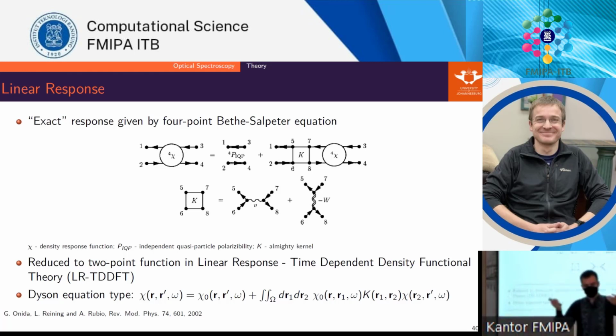So what an optical transition usually entails is the following. I have a material and I have presumably all my electrons sitting happily in the valence band in the ground state. Now I have a photon coming in, it gets absorbed. And it will excite one of the electrons into a conduction band. It will now be sitting up here at high energy. And it creates a hole where it was before in the valence band. Now the electrons in the valence band had a certain number of charges. Now we remove one, the charge changed by one. You remove this electron to a conduction band, you add a charge there. So basically now you have a negative free charge and a positive free charge. They will interact, right? Coulomb interaction.